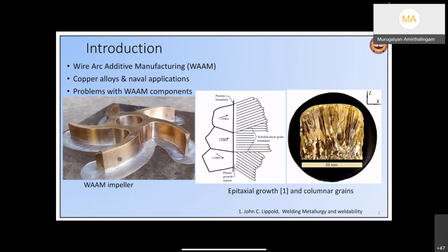The prime problem when we actually want to print, or even when you weld the copper, is this. We have a substrate over here, so this is the substrate. The moment you deposit a first bead, the molten material which is in contact with the fusion boundary, the substrate, solidifies because of the prevailing temperature gradient, and primarily in a directional, planar manner. In metallurgical terms, we call it an orientation relationship with the substrate grains. And subsequently, when the solidification progresses, the grains tend to grow along the heat extraction direction.